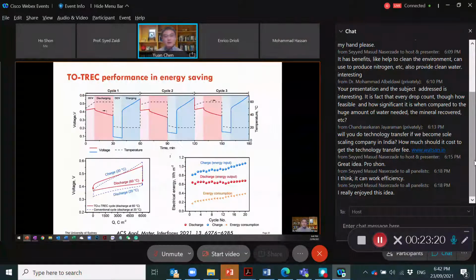So here you can see, first we want to verify, can we really extract electrical energy from the system? Because theoretically it works, and in practice it may not work. So here we try 3 cycles. This is a cell, then you put it into a 60 degree solution. When it's stable, then we do the discharging for 20 minutes. Afterwards, we take it out and put it into a low temperature 20 degree solution to recover the lithium. And then that's a charging process that goes on for 20 minutes. And so this is repeated for 3 cycles.